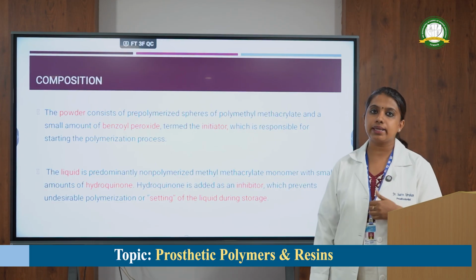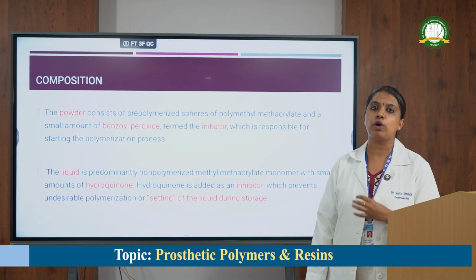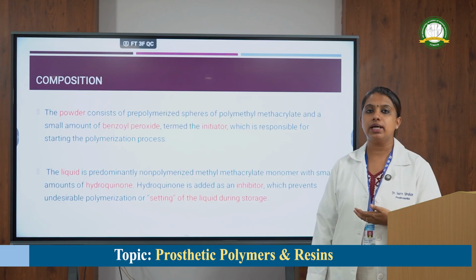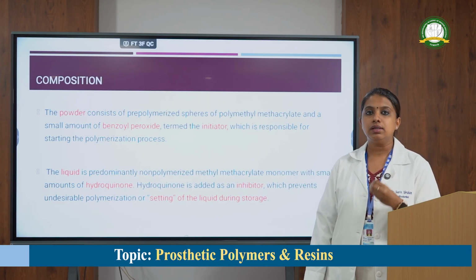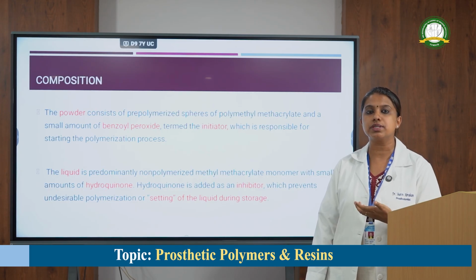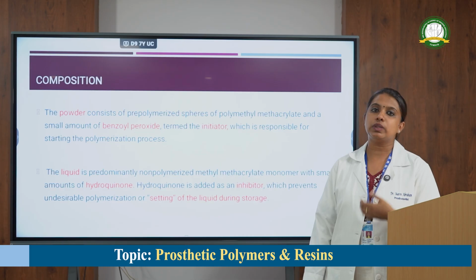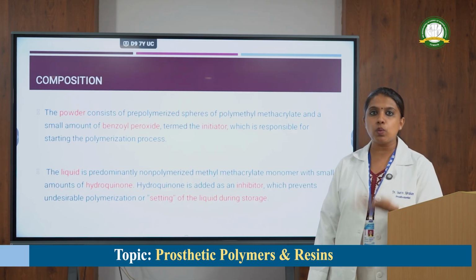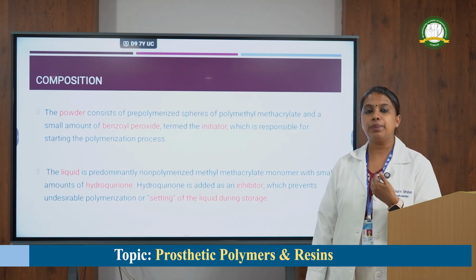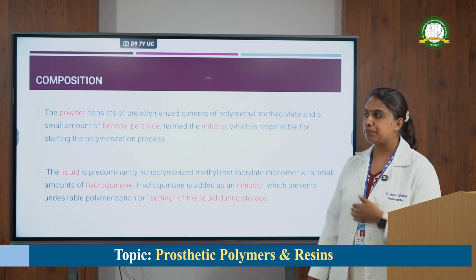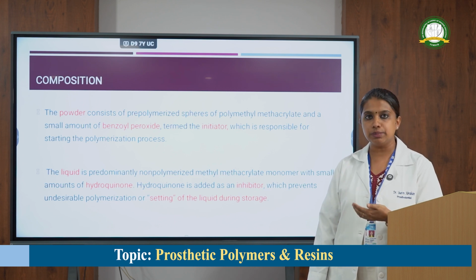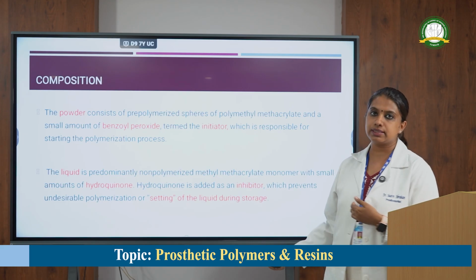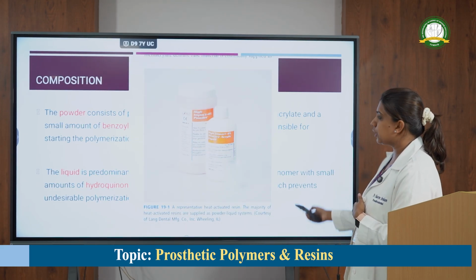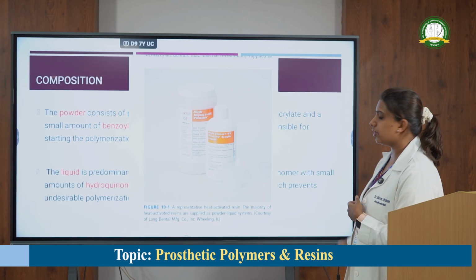Now, one of the main reasons why a fraction of the material is pre-polymerized in the powder: the researchers found that when the powder and the liquid were mixed together, the volume of material shrunk. There was a 21% volumetric shrinkage seen when the powder and liquid were mixed together. So in order to overcome this volumetric shrinkage, they decided to pre-polymerize a fraction of the powder beads. The powder is also called the polymer and the liquid is also called the monomer. These are synonyms. This is a picture of the powder and liquid that is available in the market.